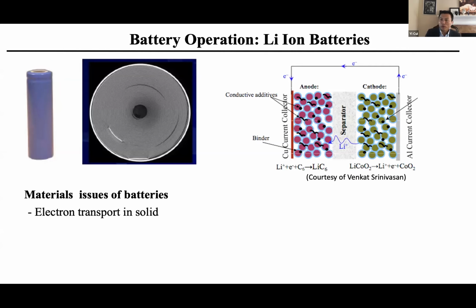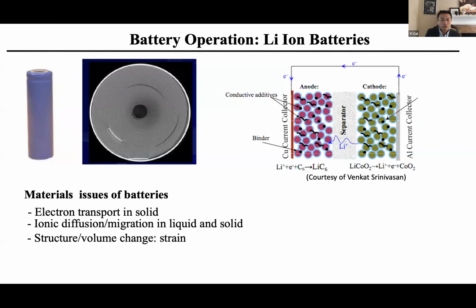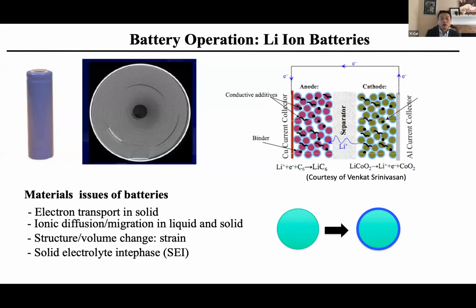During the operation, electron transport is needed, and ion diffusion is needed in the liquid electrolyte. These are liquid, carbonate, flammable electrolytes. And also in the solid state there are particles, whether graphite or the lithium metal oxide cathode. There is structure and volume transformation going on there, and there will be strain buildup. And also remember the interface between the electrode and the electrolyte, particularly on the negative electrode, the graphite side, the SEI, the so-called solid electrolyte interphase. That's the self-decomposition compound of the organic electrolyte, coating these particles with a very thin layer in the order of 10 to 30 nanometers, with the ions coming in and out, and this will be affected by the temperature quite a bit.